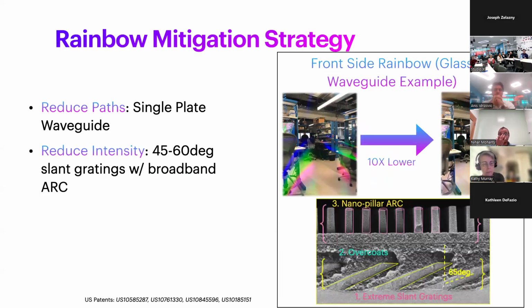This architecture is so efficient in reducing the rainbow that with optimized unit cell architecture, unit cell for the gratings, the front rainbow for even the glass devices is significantly suppressed, as you can see in the image. The grating slant in the unit cell on the bottom shown was up to 65 degrees with high index grating layers and low index grating immersion layers that we called overcoats with a moth-eye ARC on the top. We believe this to be one of the most sophisticated SRG grating-based waveguides in the industry.